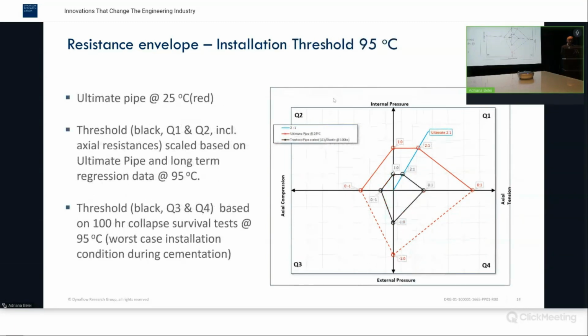So if we then look at the resistance envelope for the installation at 95. So the 2-1 is based on a long-term pressure test. So that's this black point. And actually that is the LCL value that is constructed from a regression test. So that gives you a ratio between this point and this point. And the idea is to construct the black threshold line from that. And that provides these points which are scaled according to the same ratio as indicated.